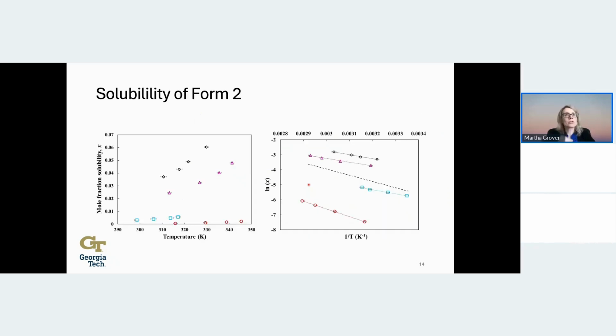And then we also measured the solubilities. And we can see here, again, we have the acetonitrile, and we have the acetone, and we have the alcohols here. So it looked pretty similar also on the Van't Hoff plot. We also had straight lines associated with these different forms. Again, the acetone is sort of more near the ideal limit, whereas the acetonitrile is definitely on the side that is favoring crystallization, phase separation.